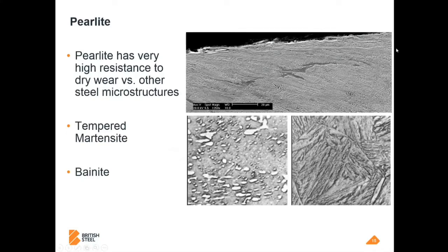There's a little bit of slip here, and you can see that deeper down into the bulk microstructure, you've got just randomly orientated pearlite colonies, but nearer the surface, you get this wire drawing type effect. If you think of high carbon wire steels, where they draw them down to really boost the strength, you can get something crazy like 2000 megapascal tensile strength on deep drawn high carbon wires for bridge cables. We're getting the same effect at the surface of the rail. So all of the pearlite lamellae are aligning with the deformation, and you end up with a particular angle relative to the surface.